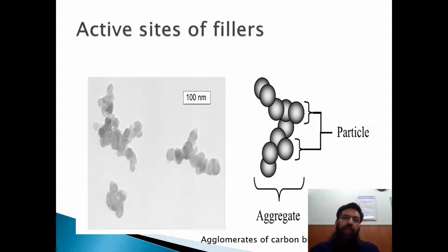Then the active sites which are present on the surfaces of the different fillers are very important. Due to those active sites, sometimes different fillers can interact with each other to make the aggregate and the agglomerate of the fillers. And when we make the compounds using those fillers having the aggregates and agglomerates, it's difficult to disperse those fillers in the plastic and in the elastomers. So we need a very high shear to disperse them in the polymers. Mainly the presence of the aggregates and the agglomerates is due to the presence of the active sites on the surface of the filler particles.